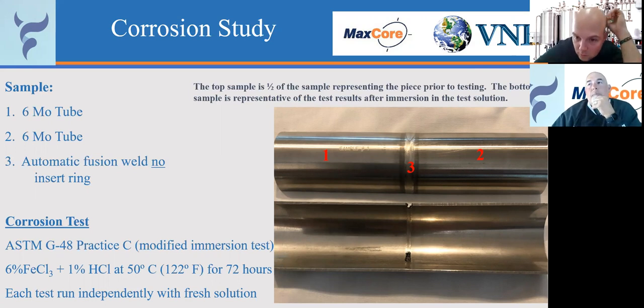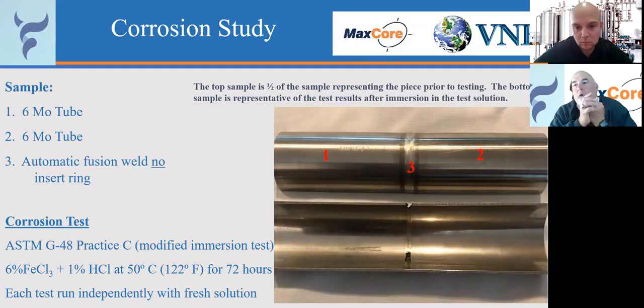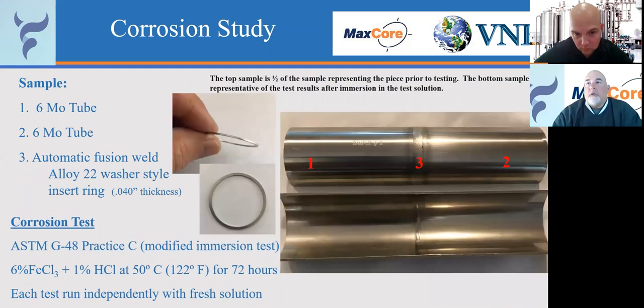So that shows you that the susceptibility to corrosion in the weld area is high when it comes to these types of materials. One of the things that we can do in order to combat that is you over-alloy these particular welds. So in this particular case, what we're using here is a weld insert ring made out of alloy 22. This is a flat washer style ring that basically fits in between the two pieces of tube, has the same OD and ID as the tube, and is about 40 thousandths thick. And like I said, it's made out of alloy 22. In this particular case, you do the same test and you can see there's absolutely no attack in the weld or the heat affected zone of the material itself. By over alloying those welds, you put that high nickel into that weld area, making it less corrosive to the product.